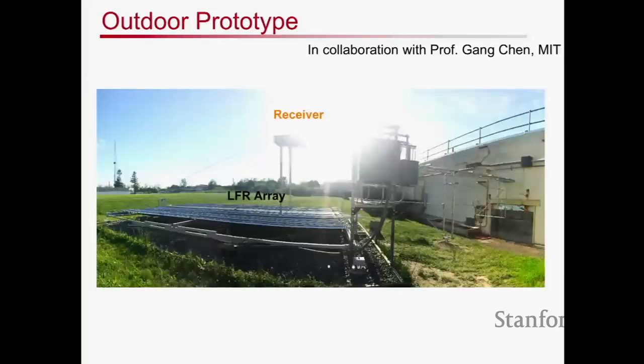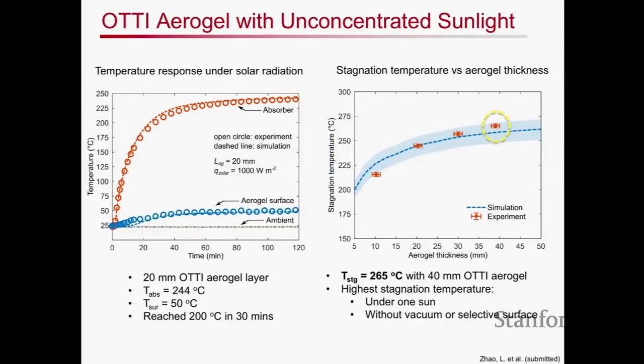So here is a stagnation temperature as a function of the aerogel thickness. As you obviously increase the thickness of the aerogel, there could be trade-offs in terms of the transparency of the aerogel, but also improving the insulation properties as well. And as we increase the thickness of the aerogels, we've been able to reach even greater than about 250 degrees or so. And so this has been really exciting. Imagine this is just with one sun, right? And without any vacuum or selective surface.